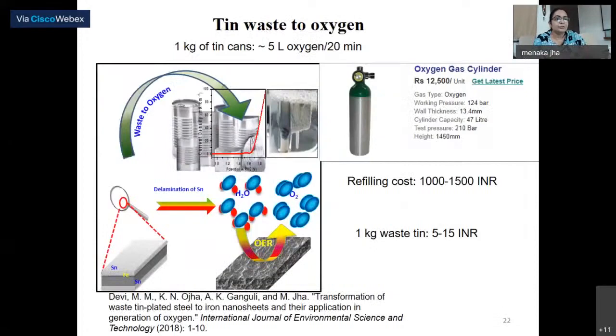When I looked closely, I saw very nice iron sheets formed at the surface of the iron. And iron is a very good oxygen generator if you apply a little bit of potential. So I took this sheet, delaminated it, created the iron sheet, and ran one simple cyclic voltammetric study. You can see at this position you can get quite a good amount of oxygen.